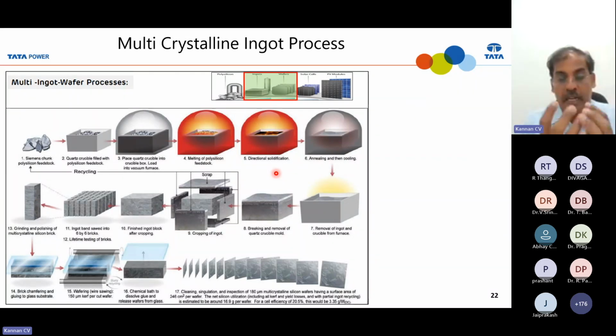But since it's a sudden cooling from the bottom, you may not expect pure crystalline. It will be a multi-crystalline format, because you are quenching: you have molten the complete silicon, then suddenly you start cooling. So you may not expect a good crystalline nature on the bottom. There will be a multi-crystalline nature generated on the bottom of the crucible. Then the multi-crystalline crystal will start growing like this, so that there will be a columnar growth all the way